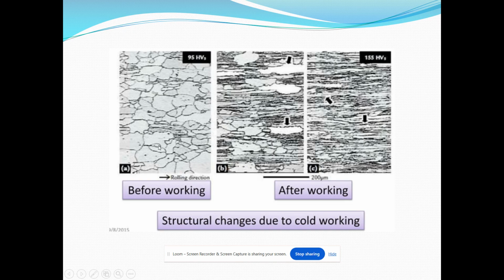This is the microstructure before the cold working operation. Here, this alloy, almost steel, exhibits a hardness value of 95 Vickers hardness number. During cold working, grains are getting elongated. After severe work hardening, after severe deformation, the grains are elongated, and you can only see the grain boundaries. Here the hardness value reaches from 95 to 155 Vickers hardness number.